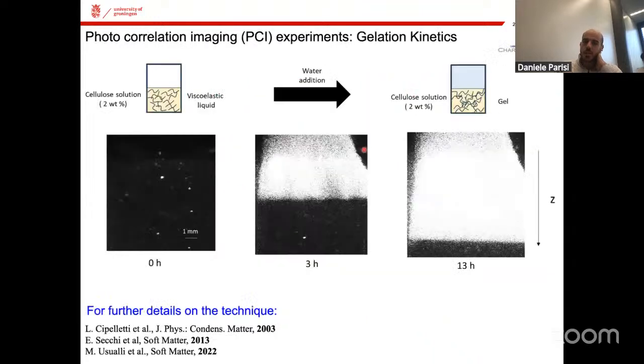So we look at this phenomenon via photocorrelation imaging or photocorrelation spectroscopy. Basically, it's a sort of dynamic light scattering technique where you can have information about correlation functions, or decaying correlation functions, in terms of time, but also in terms of position. So the experiment was quite simple. We had a capillary. We inserted cellulose solution, which is a viscoelastic liquid, in dry conditions. And then we started adding a water reservoir on top of this cellulose solution. And then we were monitoring how the water diffuses inside the solution.